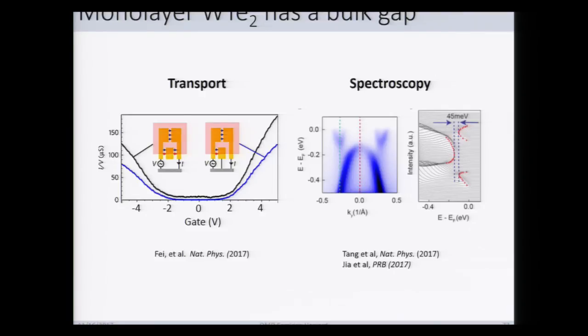In the transport devices, you see that they've done some clever device geometry techniques to show that here in blue, they're probing largely the bulk conductivity, and they see that for a range of gate voltages near charge neutrality, the bulk conductivity is actually 0. And if you allow for looking at currents flowing along the edge, you see some edge conduction that is there in the system. So this was very promising results towards determining the system as being a possible topological insulator. In spectroscopy, both scanning tunneling spectroscopy and angle-resolved photoemission have found that there is a band gap of around 40 to 50 millielectron volts in the system, and you can see these beautiful band structures that give us information of actually maybe how we should do the calculations to understand the band structure of the system.